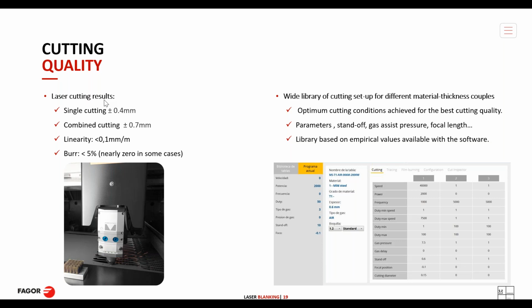burr is always below 5% and in many cases nearly zero. Additionally, a library is available for different materials and thicknesses couples in order to achieve the best cutting conditions and the best cutting quality. Parameters such as the standoff, this would be the height of the laser head to the strip, the gas pressure, the focal length, and so on. Well, the library for different materials and couples is available and optimized for each case.